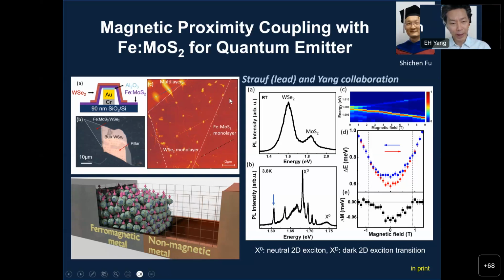Now, let's go back to the left image here. When you combine this with the iron doped material, this iron doped molybdenum sulfide is a ferromagnetic material. And the bottom left shows that the ferromagnetic property can be induced into a non-magnetic material through this magnetic proximity effect. But this proximity coupling is very thin. You can go maybe a nanometer or sub-nanometer, but luckily tungsten diselenide is what, point something nanometer. So basically this whole material becomes ferromagnetic.